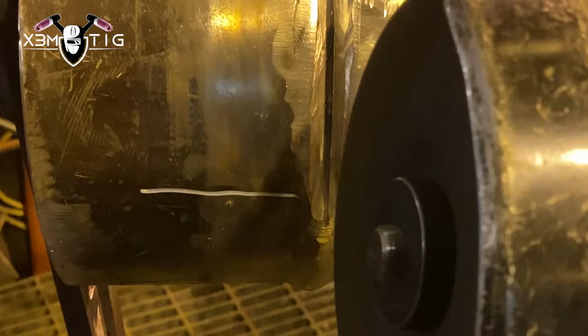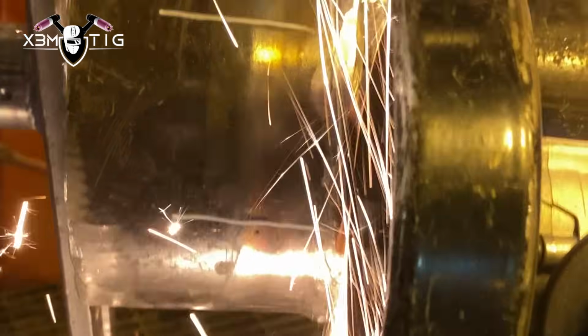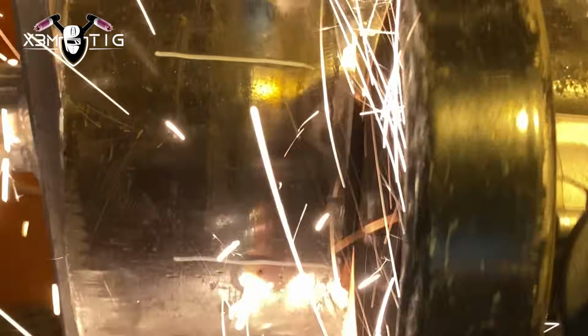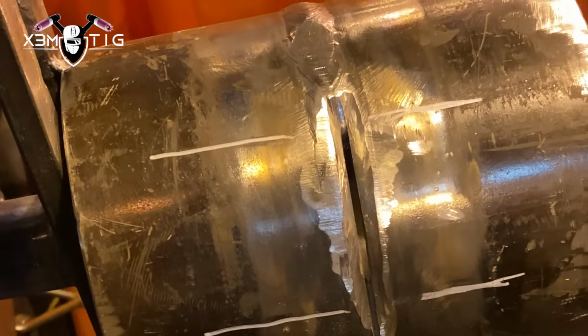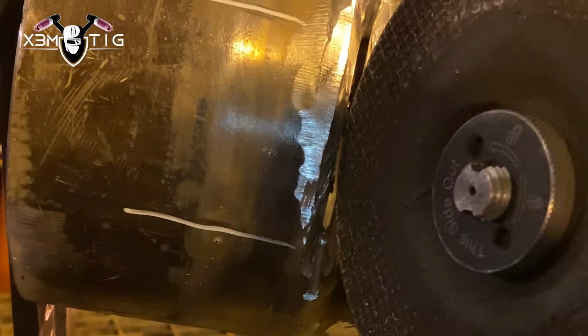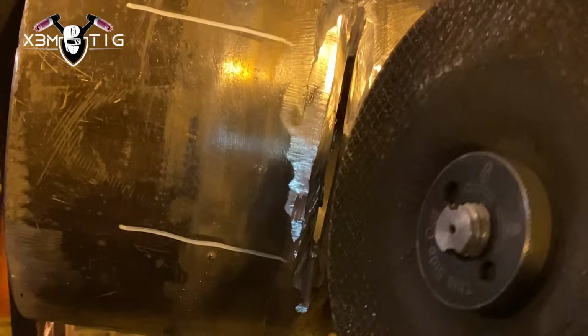This is one of the most common repairs, especially with TIG welding. Porosity can be caused by, as I said, several factors. It can be all the loose parts on your torch. You know, there's a gas leak above or underneath your torch head. That can cause porosity as well. Bad preparation on your pipe, you know, there's oil and grease and things. It depends on the material as well. If you guys didn't follow the procedure very well, or the pipe should be baked out and it was in service before, it's just to replace one section. That's what usually causes it, especially on carbon.